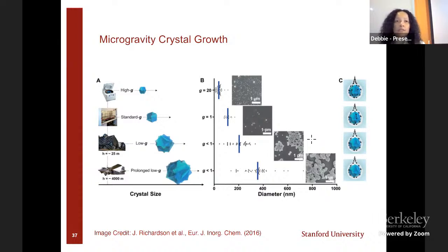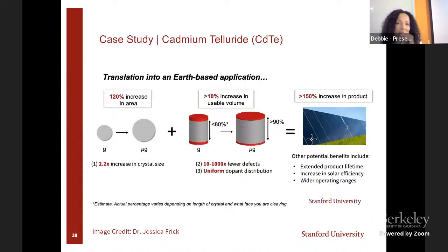If you go back 50 years, they were growing gallium antimonide crystals, large format, on the space shuttle with higher growth rates and also reduced defect density. So what does that mean for semiconductors? This is one case study. If you grow a cadmium telluride crystal for solar cell applications on Earth versus microgravity, in microgravity you can get a larger area. Also, that translates to more usable volume of material if you're able to suppress the defects in the material as well. So again, the absence of thermal convection in your fluid as you're growing this crystal creates a more diffusion-based growth as opposed to having defect sites during growth. And this would translate to more product that we want to use here on Earth.